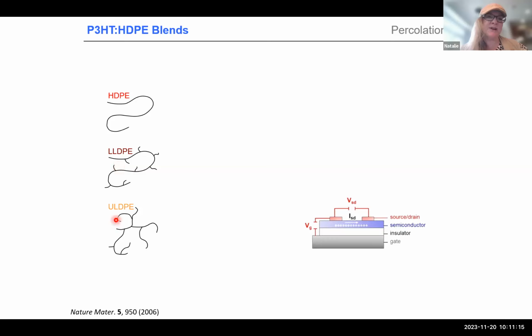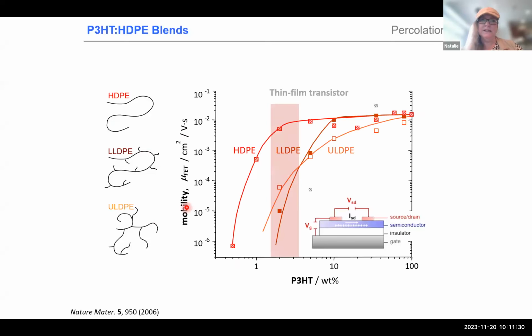We added 3 different types of polyethylenes: high density, linear low density, so they have some branches, and ultra low density, which is not a linear polymer anymore. It's more like this mess where the branches start to be as long as the backbone. And when we extracted the mobility from these transistor measurements, you see, when you get the mobility of the P3HT here on the right and add polyethylene, we could really add a lot of polyethylene, 99%, and still have the same mobility. And when we used a bit less ordered, so more amorphous materials, we still had a pretty good threshold of